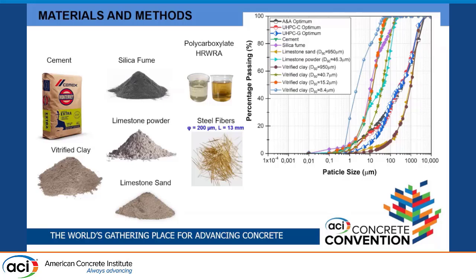So what do we use? We use silica fume, of course, a polycarboxylate high-range water-reducing admixture, limestone powder that is produced by the grinding of a limestone aggregate in Monterrey, Mexico, vitrified clay, limestone sand, and the steel fibers. Those that you see in the picture are the first generation of fibers used to produce this kind of concrete. Now, the company Bekaert, the name is Dramix, has a new generation of fibers of this type. But now, also in the market, you can find some polyvinyl alcohol fibers that almost reach the performance of the steel fibers. So the knowledge about ultra-high performance concretes and the materials available to produce it are becoming very popular these days.